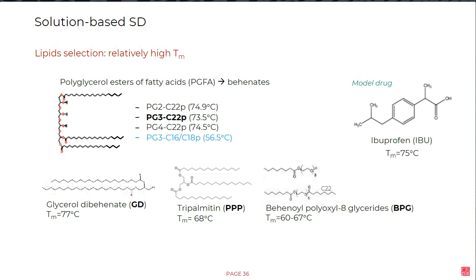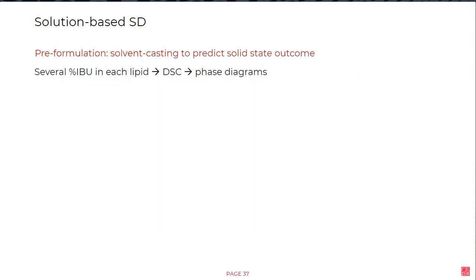I'm having here also an example of a PGFA in light blue with a relatively low melting point. This is a comparison of how important it is to provide a relatively high melting point on lipids. The other materials are glycerol dibehenates, tripalmitin, and behenoyl polyoxyl glycerides, which are also having high melting points, and as a model drug, ibuprofen. For the second part, as you remember, the pre-formulation step was quite important to carry out, and it's quite an easy and fast step. In this case, since we are spraying a solution, a solvent casting pre-formulation will give us a good idea on a prediction of the solid state outcome from spray drying.